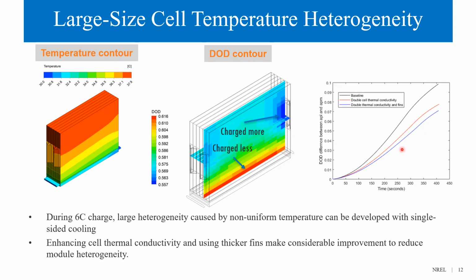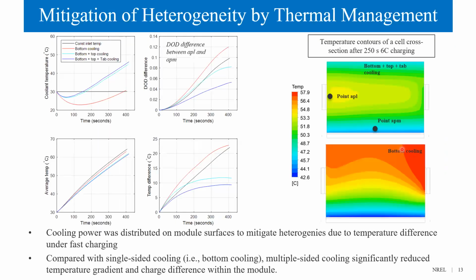Cell electrochemical heterogeneity can be reduced by decreasing the cell temperature difference. This can be achieved by enhancing cell thermal conductivity and arranging heat transfer pathways more evenly, such as doubling the thermal conductivity of the cell and using fins on both sides of the cell. Additionally, optimal design of the cooling surface to the cell is necessary.